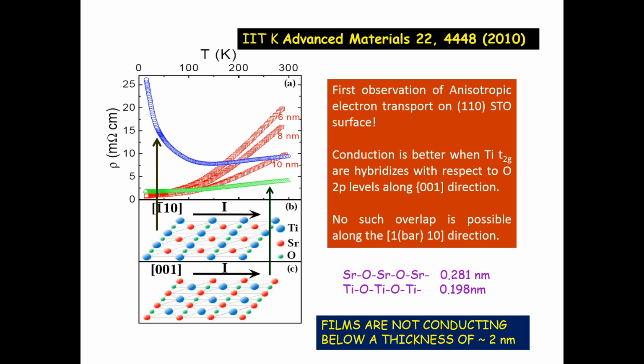On the other hand, if I take the 110 surface, and flow the current in this direction, 1 bar 10, where these are titanium, titanium, titanium, there is no bridging oxygen here, and this is the strontium line. Along this direction, the conductivity at low temperature actually shows an insulating behavior. But if I flow the current in this direction, where I have titanium-oxygen bonds, I see a nice metallic behavior. So this was the first observation of anisotropy in this 2D gas, not in LAO-STO but LTO-STO, though in LAO-STO also some groups have now seen this anisotropy.